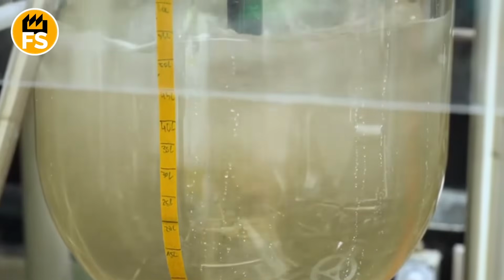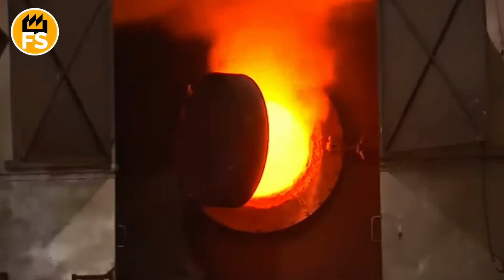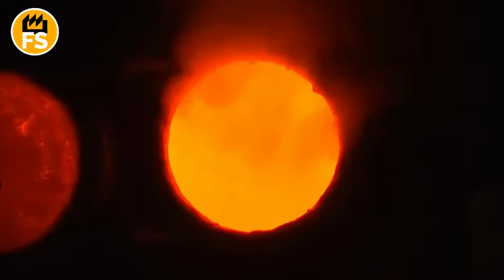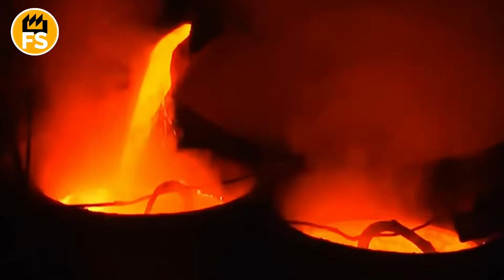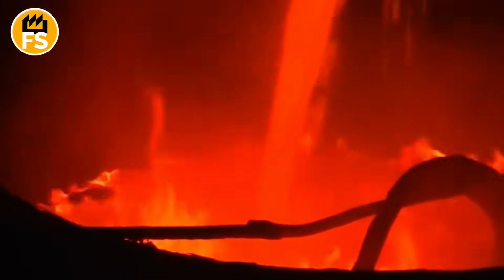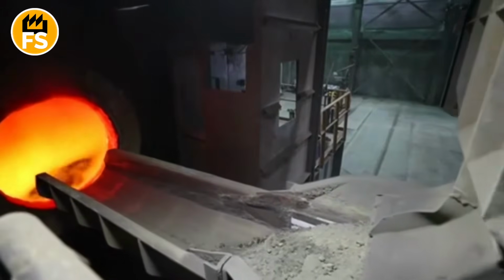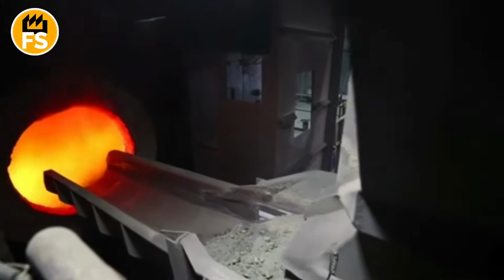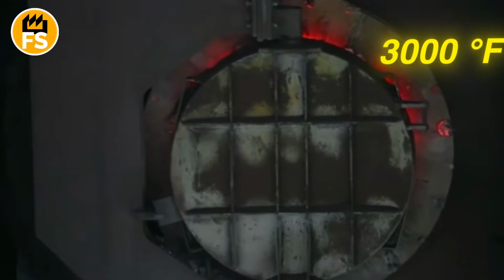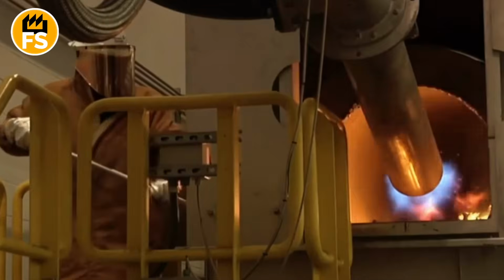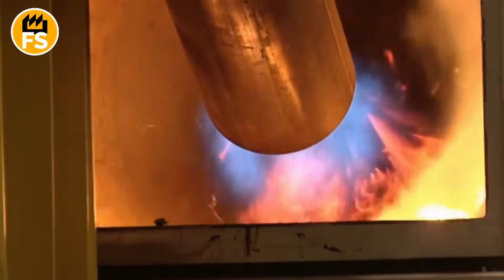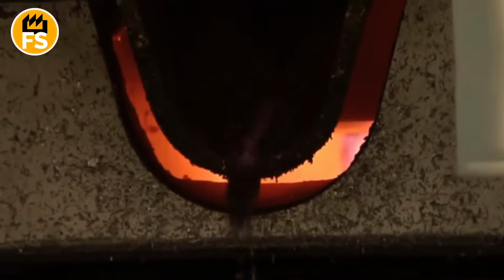If hydrometallurgy is a gentle approach, then pyrometallurgy is more like shock therapy for metals. Here, everything literally burns and melts. The black mass is loaded into a huge arc furnace, where the temperature reaches almost 3,000 degrees Fahrenheit. The metals melt into a liquid mass, and the plastic and other residues simply burn up.